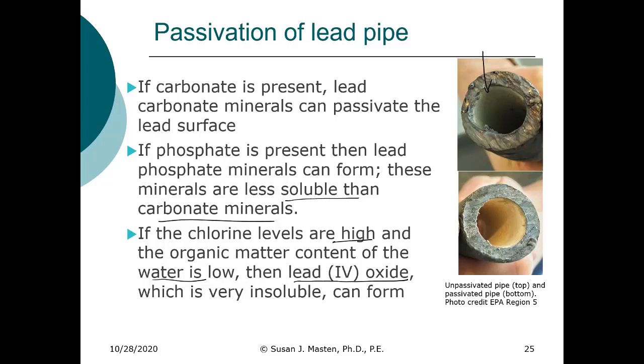And that would allow the potential contact of your oxidant, being the disinfectant or oxygen, with the metal. Here it is a yellow color. This is likely a lead phosphate coating on the inside, and it's a much more uniform coating. So what we're doing is we're precipitating, in this case, the lead phosphate, to try and protect the pipe from further corrosion.